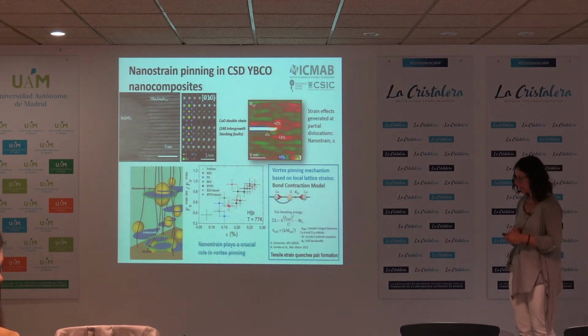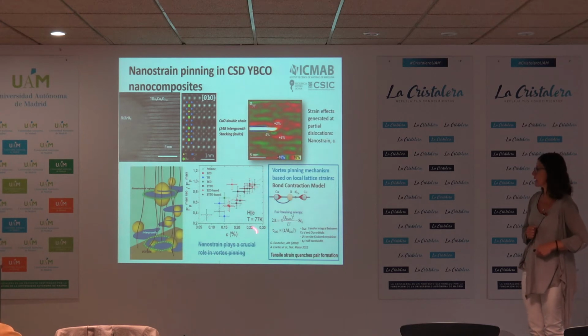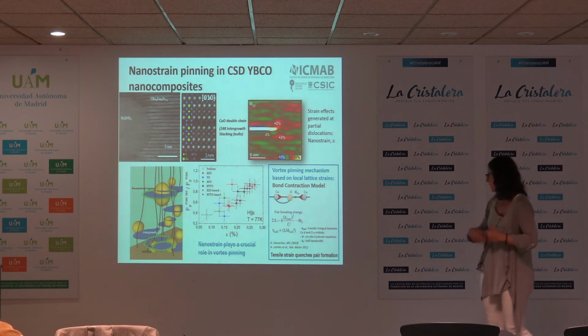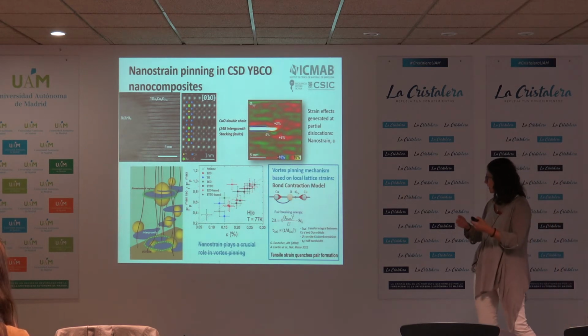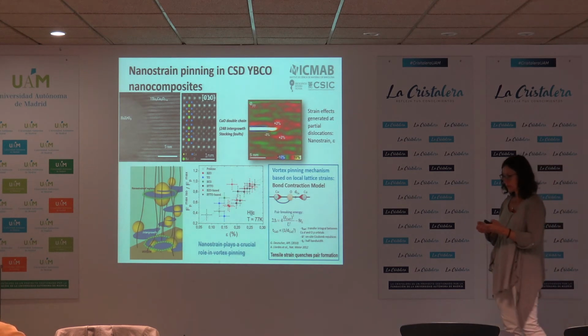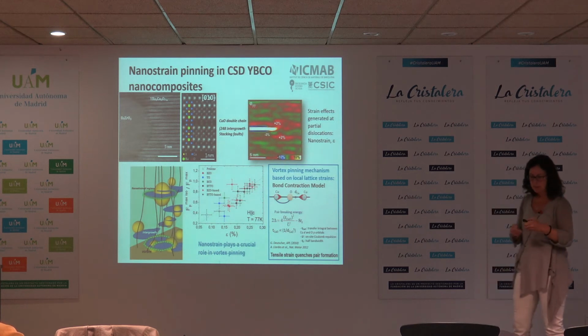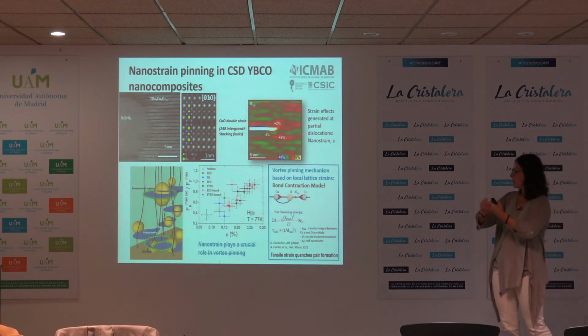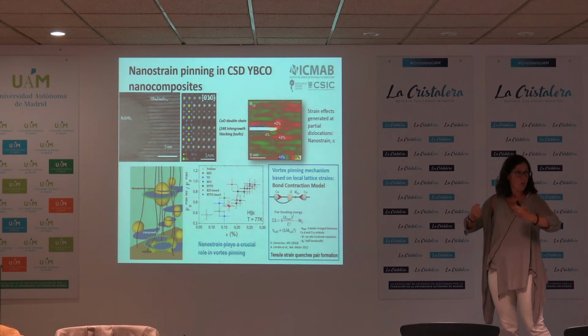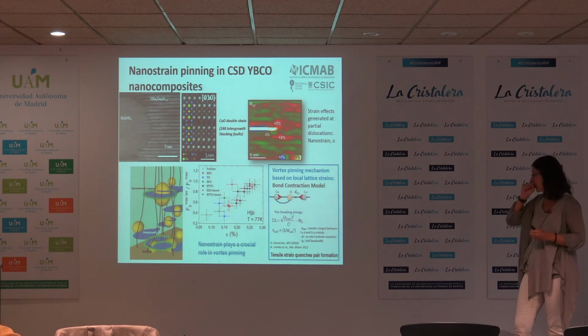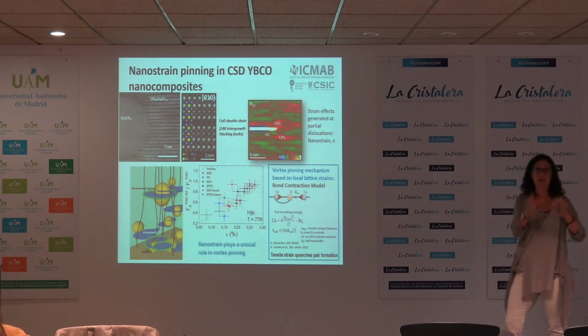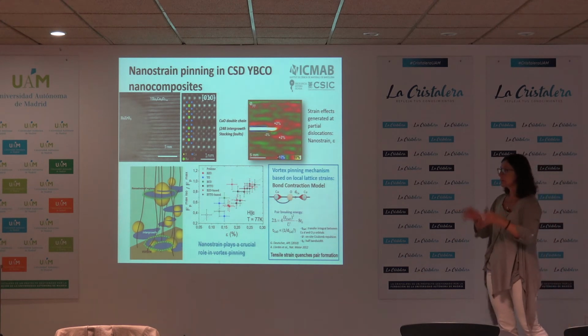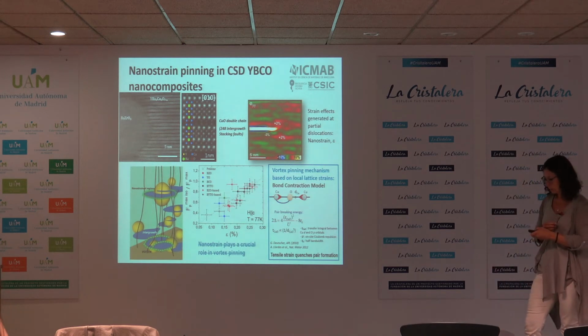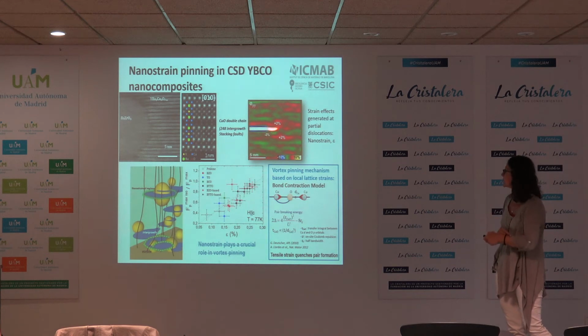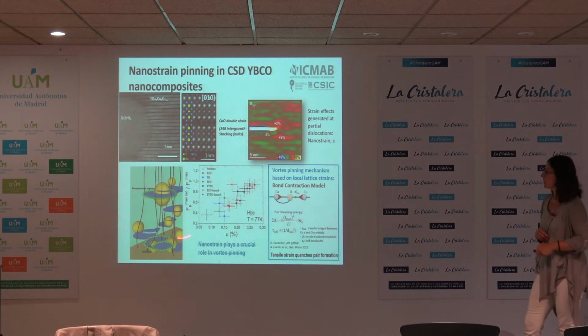And what we have been able to see is that in fact the pinning force is increasing with this strain, which can be in fact evaluated by XRD. So here what we have claimed is that in fact the strain we have accumulated into these areas is at the end lattice displacements. When the copper oxide orbitals are under tensile strain, there is no overlap, and therefore you are able to get no pair condensation in that region, and therefore if this is done in nanometric areas localized all over the material, these then can be nanometric pinning centers. And therefore this is a way to explain why this nanostrain, which is localized in a nanometric area at all the surroundings, is able to have a proportional linear relationship with the pinning force.